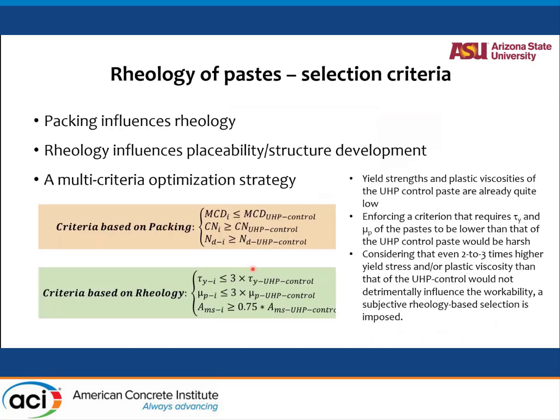So what are our selection criteria? We have all these mixes, we have done all these numerical particle packing experiments, and all these experimental rheology measurements. What is our selection criteria? We use one criterion based on packing and one based on rheology. The criterion based on packing is simply that the mean centroidal distance, the coordination number, and the number densities are either less than or greater than the corresponding values of the UHP control paste.